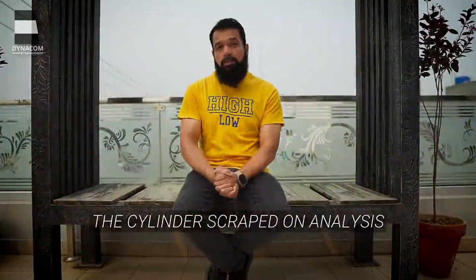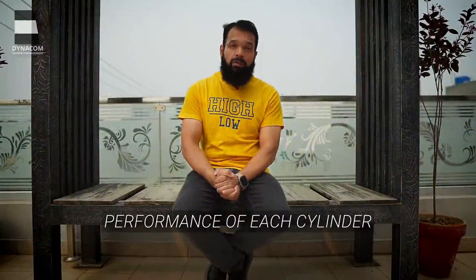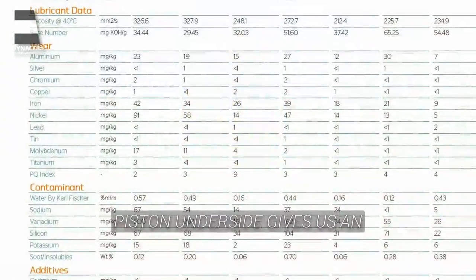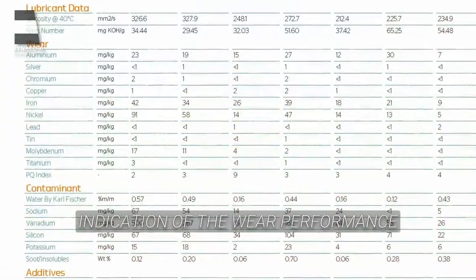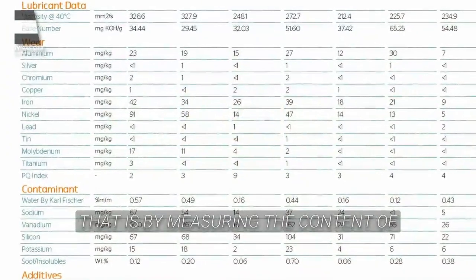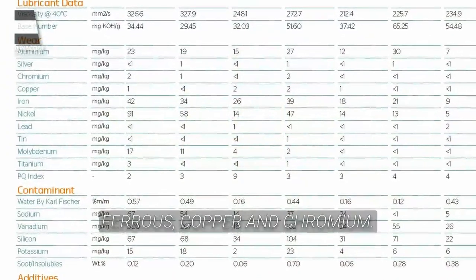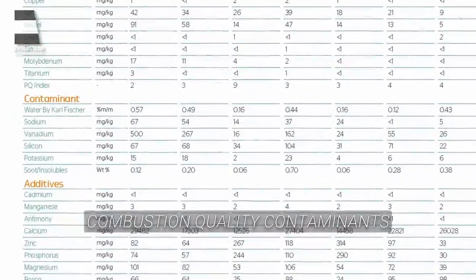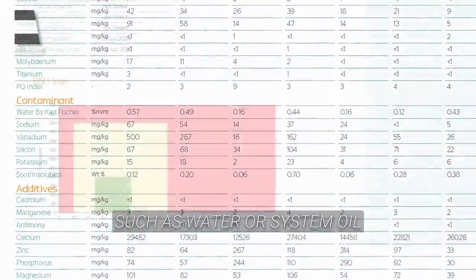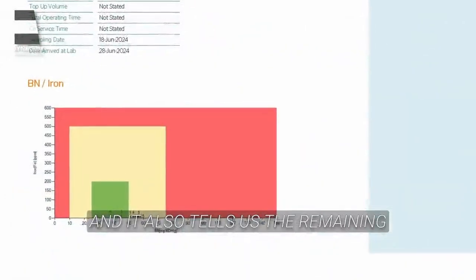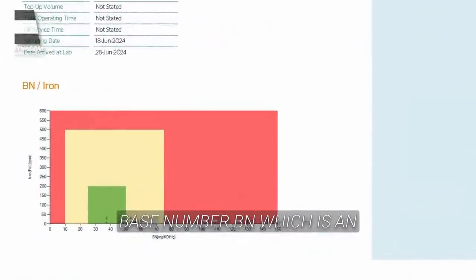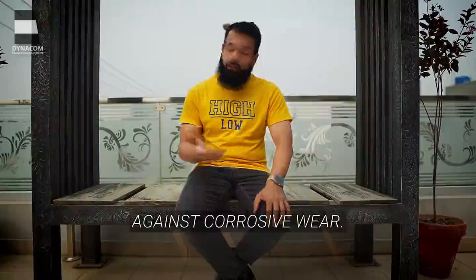The cylinder scrape down analysis allows us to assess the performance of each cylinder unit separately. The residue oil taken from the piston underside gives us an indication of the wear performance, by measuring the content of iron, that is ferrous, copper, and chromium. It also allows us to find combustion quality contaminants such as water or system oil, and it also tells us the remaining base number, BN, which is an indicator of the protection against corrosive wear.